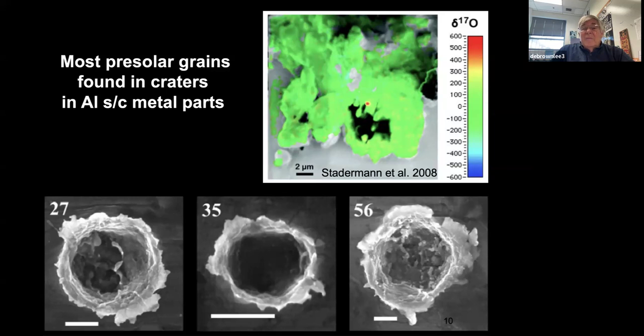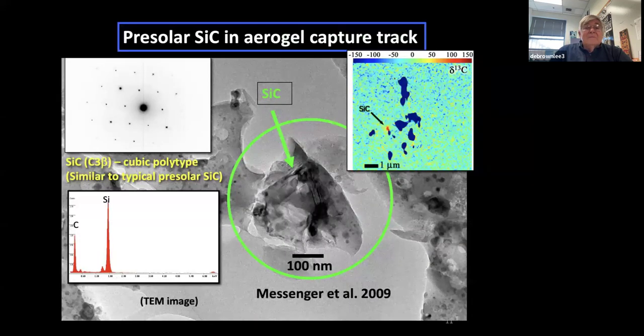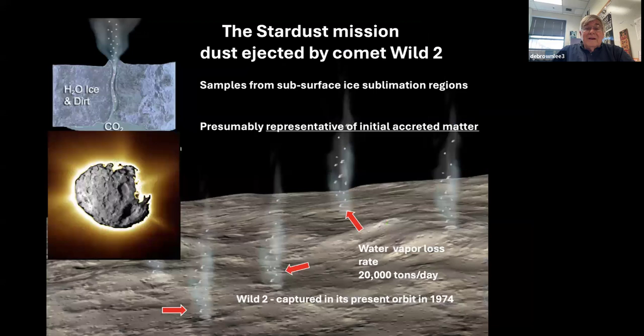This, in the upper right-hand corner, is an interstellar, a presolar grain from Frank Stadermann in 2008. There were quite a number found in the aluminum. There was actually only one so far that's been found in the aerogel, and this was a silicon carbide grain, about a half a micron in size. You can see this isotopic map on the upper right, and it's a diffraction pattern. It's from a 3C beta cubic polytype on the upper left.